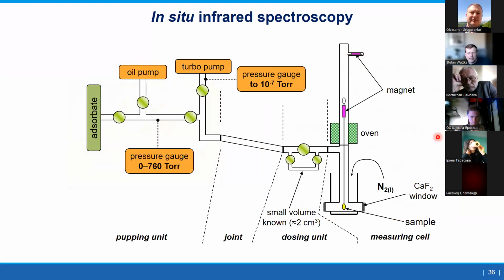And what you have is a setup. I just want to describe briefly what it looks like, so that you can really imagine this. So here you have your sample, your pressed pellet. This is a closed setup. And then you have here a small volume, and it's very important. This is the dosing unit. You know exactly the volume of this dosing unit, and so you know exactly how much you add. So these are closed valves. And then you have a joint, and then you have two pumps, the oil and the turbo pump. So at first you always use the oil pump, then the turbo pump, in order to clean the surface. And then you have here IR. You can measure IR here.